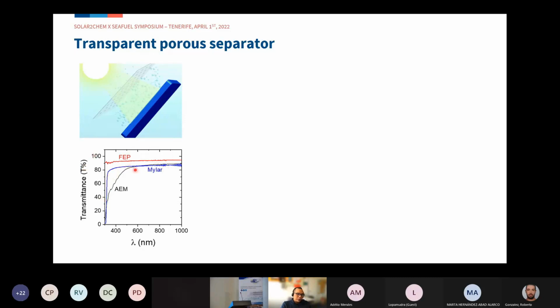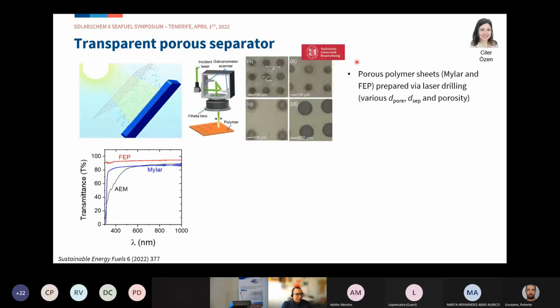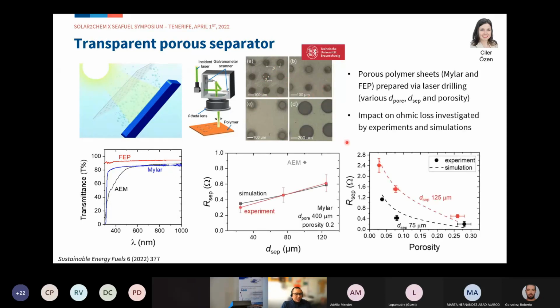The transmittance of these two films is shown over here and compared against an anionic exchange membrane. As you can see, it's performing better, especially the FEP, which shows more than 90% transmission across the entire spectrum. Using this, Ciler, a postdoc in my group, collaborated with our colleague at Braunschweig, where they laser drilled these porous polymer sheets to introduce the porosity. So we can tune our pore diameters, the pitch length, and the porosity, as well as the thickness of the separator, and we investigated using experiments and simulations the impact of these separator properties.